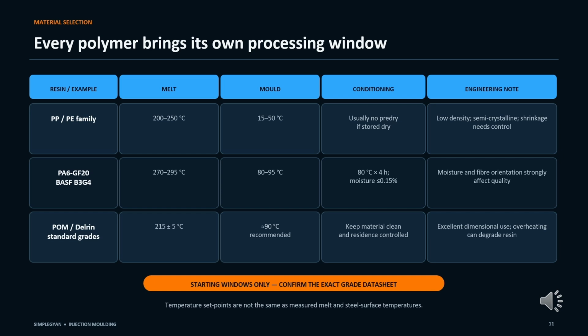A 2025 Formosa guide gives a PE and PP melt window of about 200 to 250 degrees Celsius and mold temperatures around 15 to 50 degrees. BASF data for a glass-filled PA6 grade, Ultramid B3G4, recommends roughly 270 to 295 degrees melt, 80 to 95 degrees mold, and pre-drying at 80 degrees for 4 hours to very low moisture.